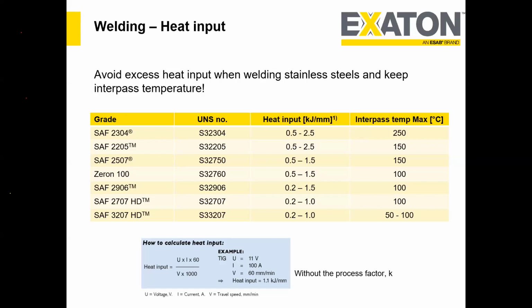Higher the heat input or higher the interpass temperature, you are basically increasing the temperature of the base material. Now, when the liquid weld metal cools down, your gradient is low, so it has the potential to cool down slowly. If it cools down slowly, it will take more time in that critical temperature zone. If you stay for more time in the critical zone, it has a higher tendency to form the intermetallic phases. On the other hand, if your heat input is very low, which means your gradient is high, the liquid weld metal has a tendency to cool down much faster. If it cools down much faster, then two things will happen.